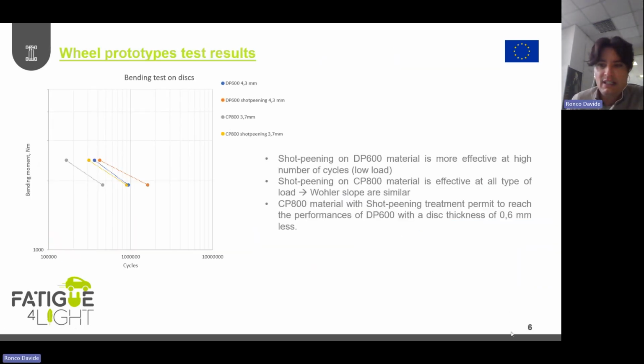Here we can see the fatigue results on the real disk, so the parts that we produced. In this graph, in blue we have the fatigue results for the current wheel, that is DP600 4.3. In gray is the CP800 3.7. As you can see, the CP800 compared to the DP600 is lower in performance, but this is normal because we reduce the thickness by 0.6 millimeter.